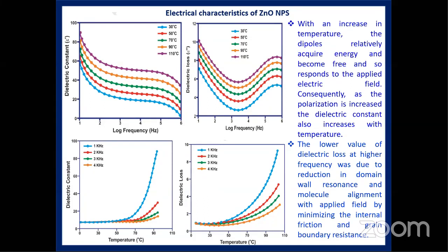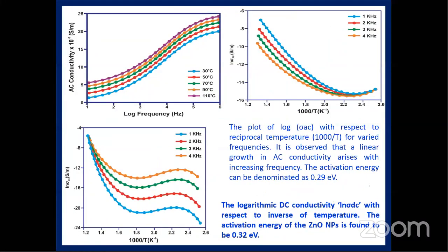The lower value of dielectric loss at higher frequency was due to the reduction of domain walls resonance and molecular alignment with the applied field. You see here the AC conductivity of zinc oxide. AC conductivity increases with increasing frequency, and also increases with increasing temperature.